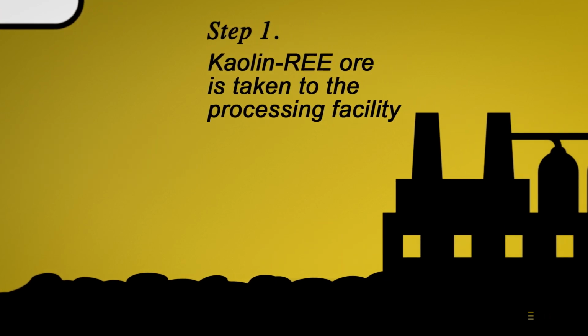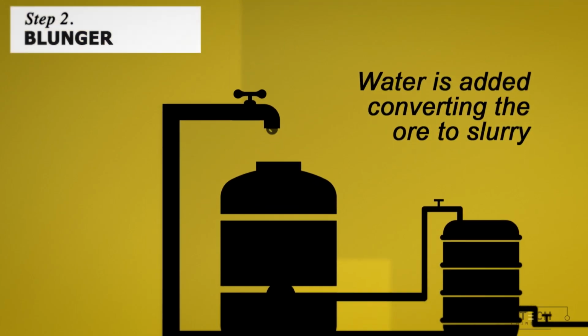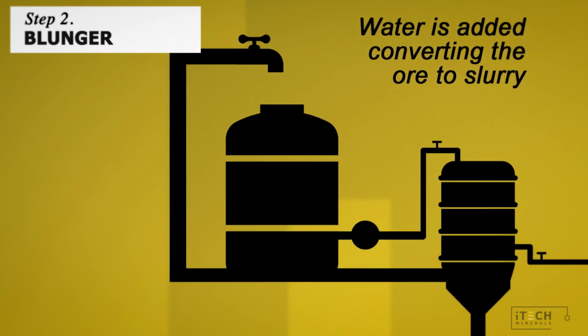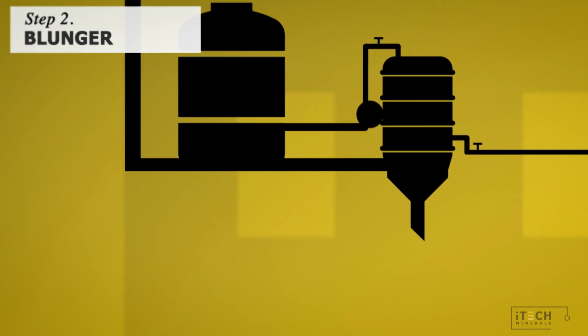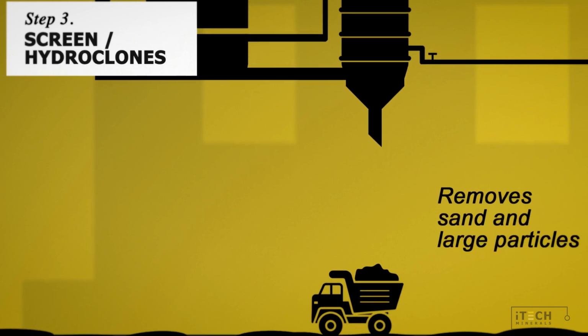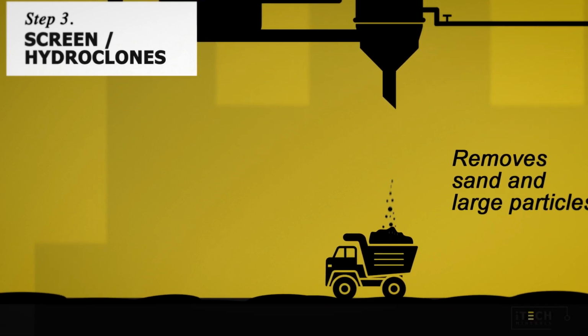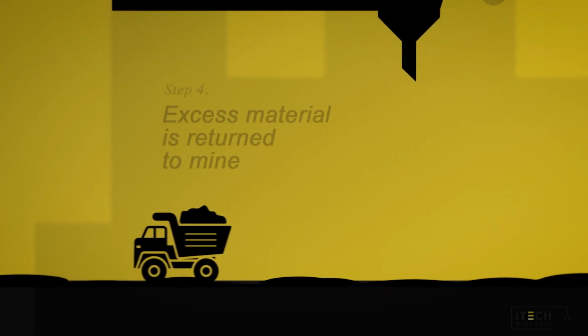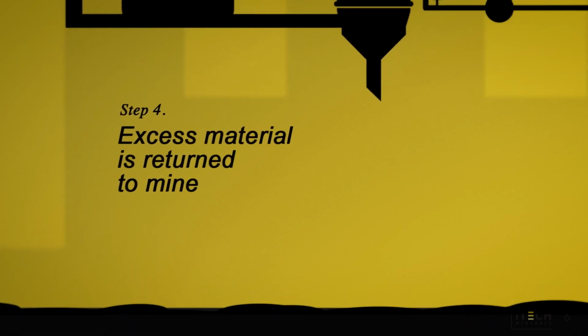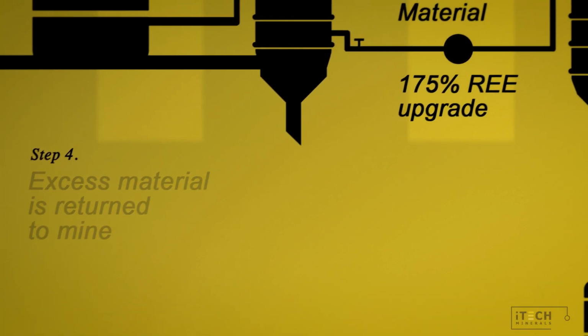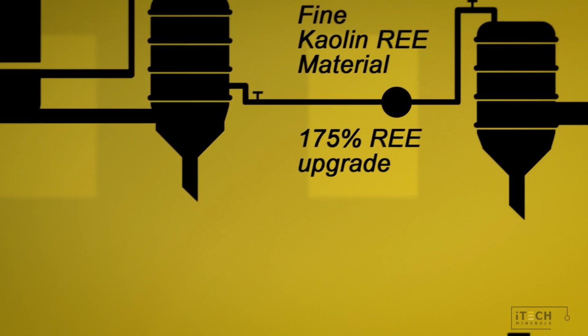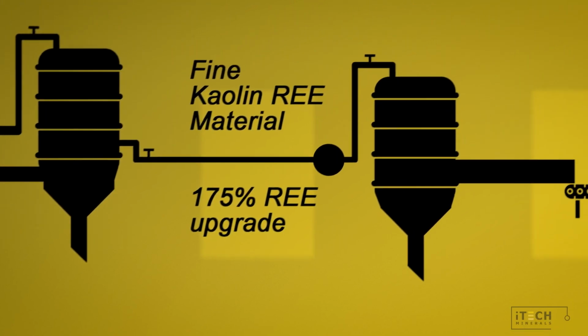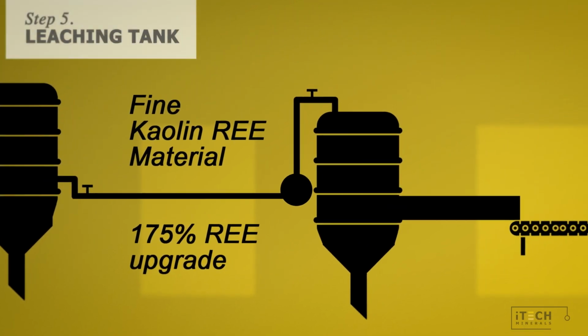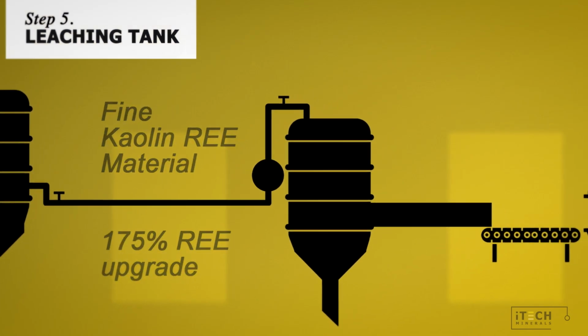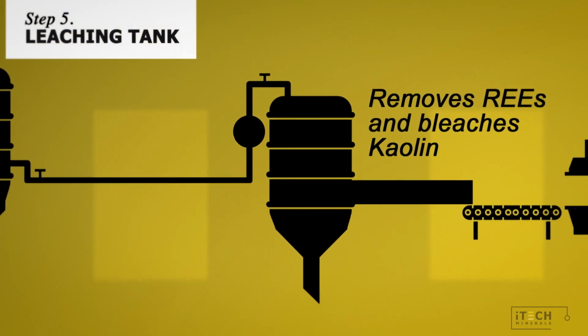We dig that kaolin rich material up, we put it into a blunger which converts it with water into a slurry, and then you can start piping it around and moving it. You put it into a screening facility or hydroclones which remove the coarse component. That removes all of the coarse quartz material and you put that back in the mine. So what you have left then is the fine material, and that's the valuable stuff. That's got the kaolin and the rare earths in it, which have been upgraded by 175%.